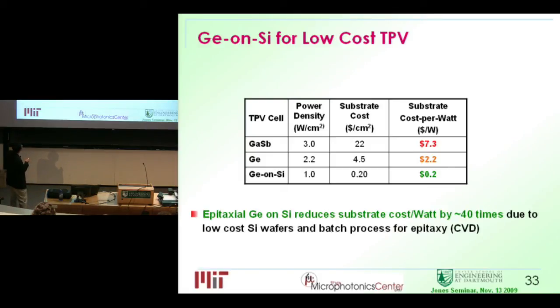But if you can grow a very good germanium layer on silicon, although your efficiency is probably not as high as these two materials, in terms of dollars per watt from the substrate, not including processing that is, it's only 20 cents. So it makes a lot of sense to do this germanium silicon thermal photovoltaic cells.